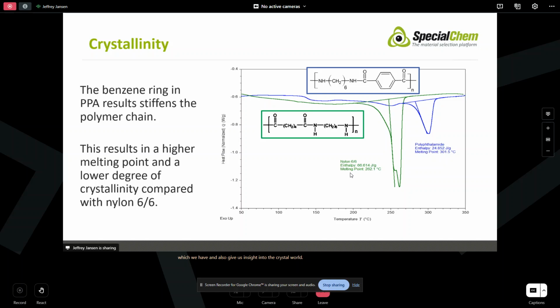Okay. In terms of crystalline structure, DSC can give us an insight into how crystalline the material is, and then the structure, together with the DSC, can tell us why. So here we have the comparison of nylon 6,6 versus polyphthalamide. Certainly polyphthalamide has a higher melting point, but it also has a drastically lower heat of fusion. Enthalpy is much lower. It's a much lower crystalline state. When we look at it, we've got this benzene ring, this relatively rigid structure that doesn't lend itself to folding back on itself to form crystals. Whereas with nylon 6,6, we've got a lot of aliphatic content, and so that actually does tend to come together quite nicely to form crystals.